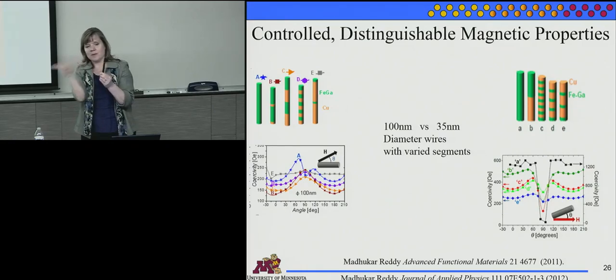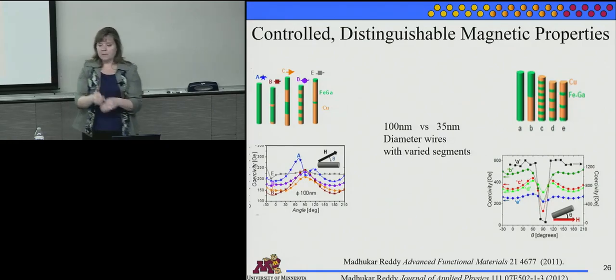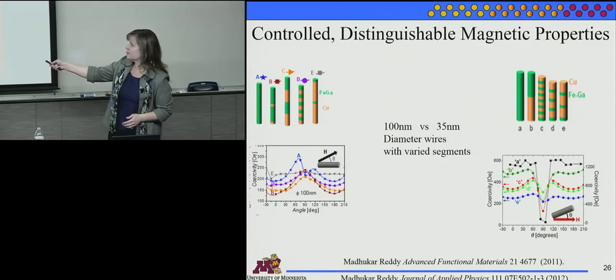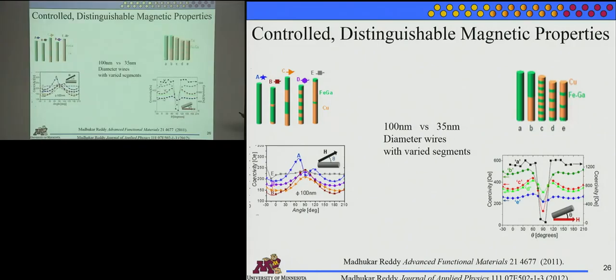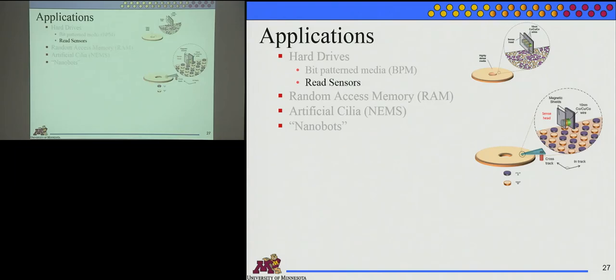Then you have to force them back down that way. So there's a minimum right at 90, and it's actually pretty interesting. This magnetostrictive alloy with 35 nanometers has a huge coercivity until right around 90. And otherwise, yeah, so it's just different.